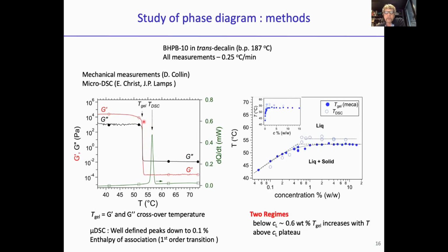And we can do this for different concentrations, and for each concentration you can map out the gel to sol transition. We did this phase diagram for a huge range of concentration, more than 2 decades. And we can observe two regimes in this phase diagram. In the first regime the melting temperature increases with the concentration, and then we reach a plateau here. And why do we get an invariant here?